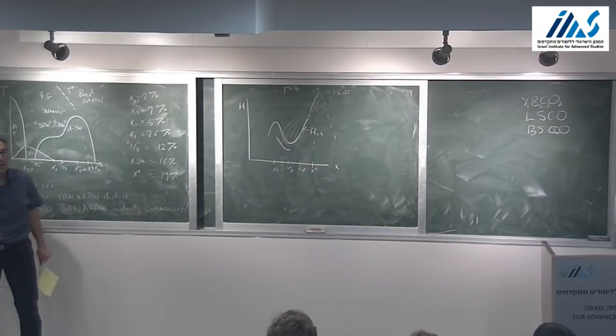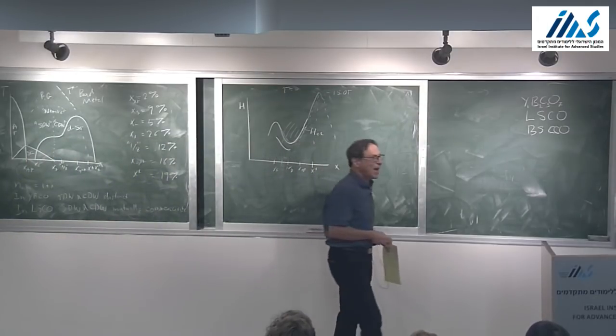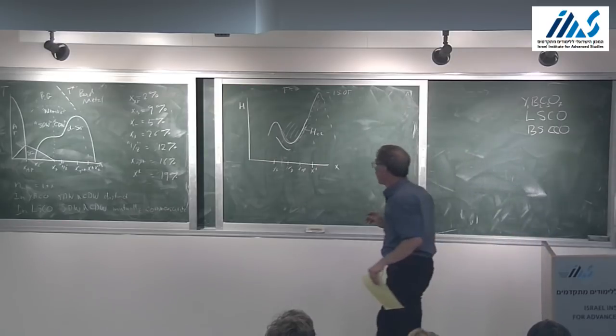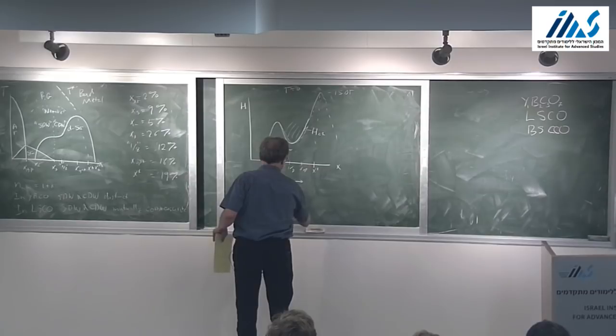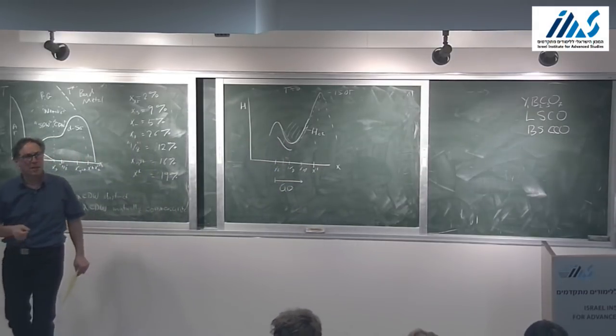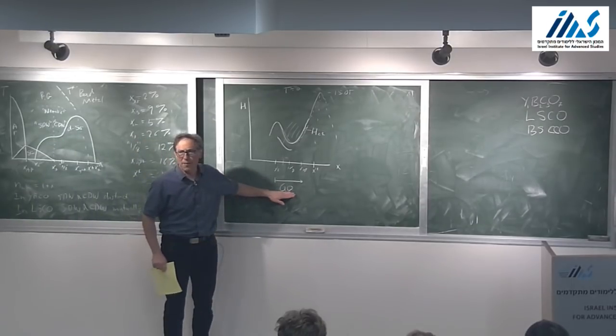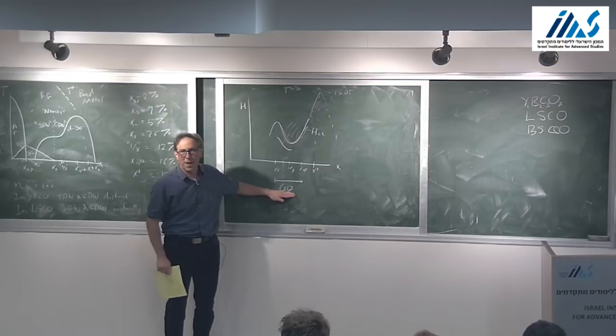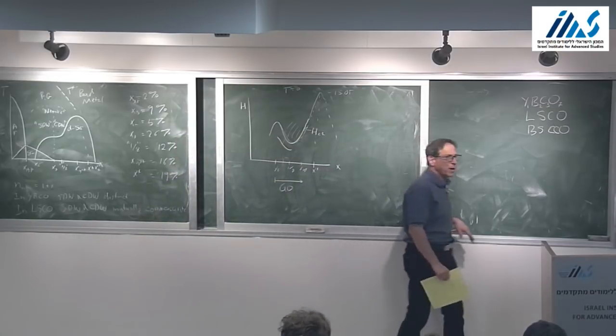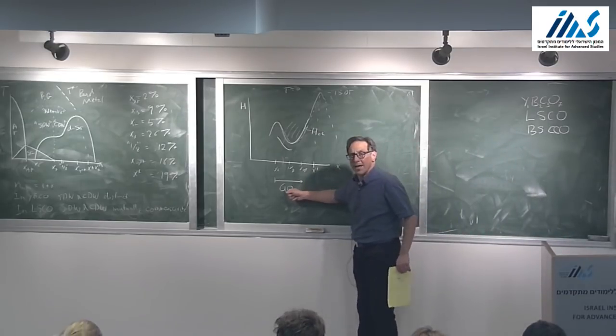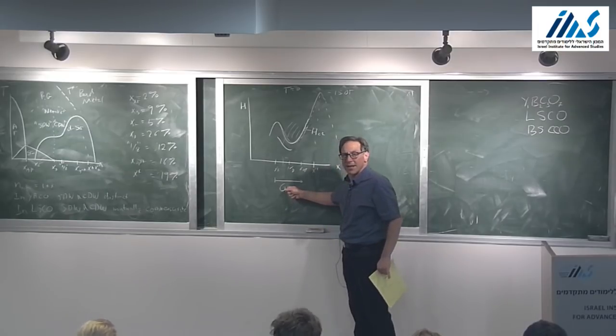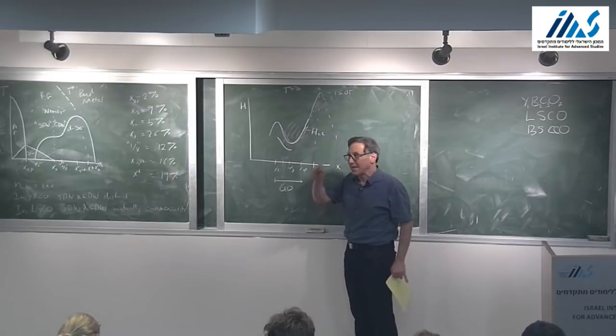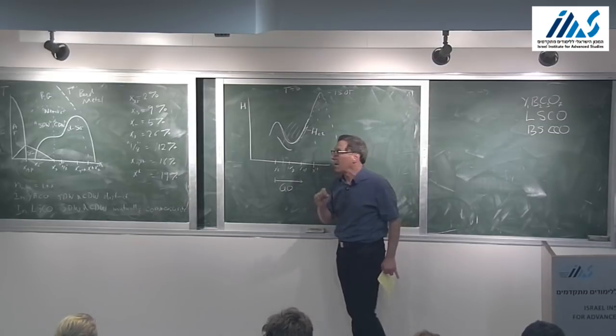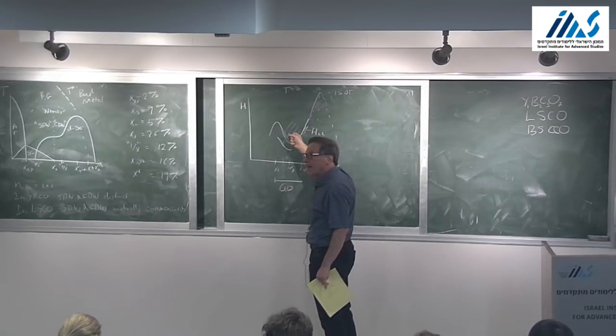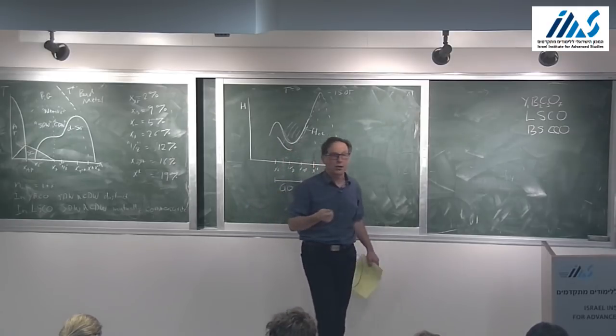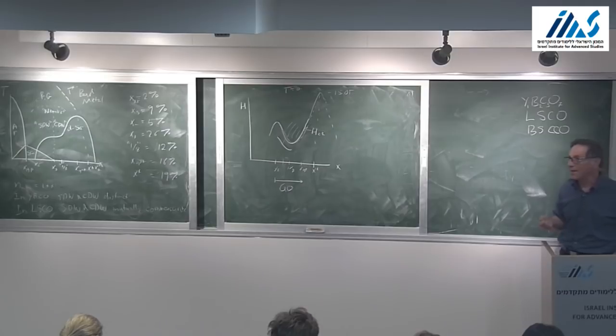which is an important regime for experiments, although the system is in a resistive state, in fact, the system exhibits quantum oscillations. So in this whole regime, the system exhibits quantum oscillations which are very clear features of a metallic state with Fermi liquid-like elementary excitations, in this case corresponding to an electron pocket. So this is not only a metal, I'll get to you in 1 second, not only a metal in the sense that it's resistive, but it's a metal in the very precise sense that it has a Fermi surface and it exhibits sharp quantum oscillations. Nonetheless, in this regime, one also sees magnetic hysteresis, which is another one of the signature features of a superconducting state.